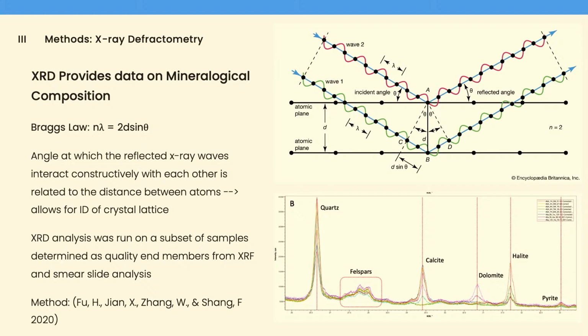The angle at which those waves constructively interact is related to the distance between the atomic planes. That's because the atomic planes have a similar distance to the wavelength of X-rays. So we can use Bragg's law, which details the relationship between the angle of constructive interference and the distance between atomic planes, where the wavelength of the incident X-rays equals the distance between the atomic planes times the sine of the angle of constructive interference. So that means we produce these spectrograms that you see on the bottom here. On the y-axis, we have intensity, and on the x-axis, we have 2 theta, which again, theta is the angle at which constructive interference is occurring.